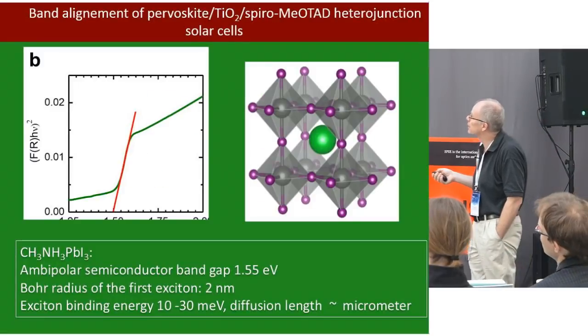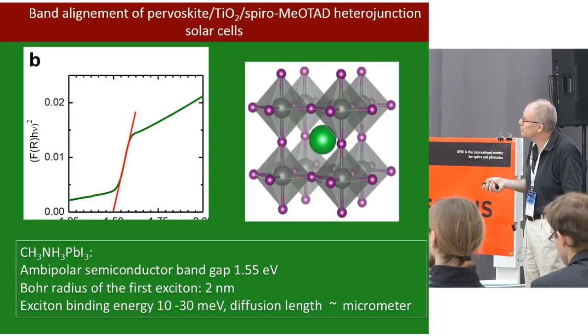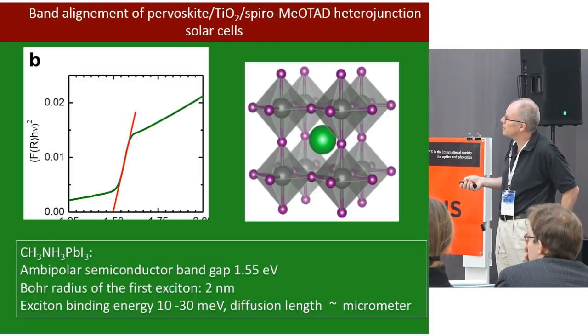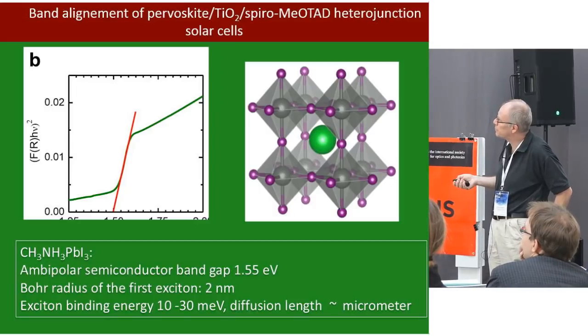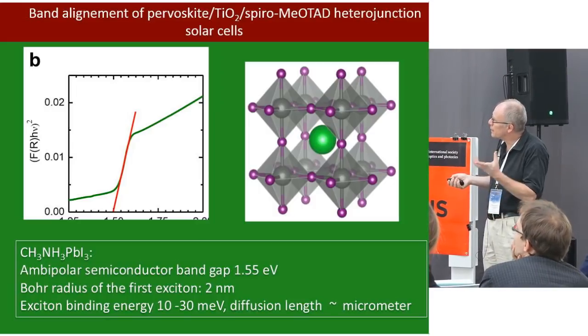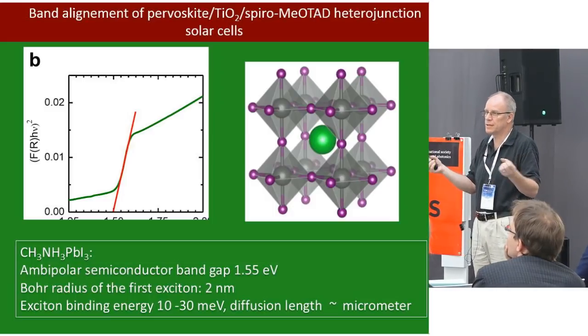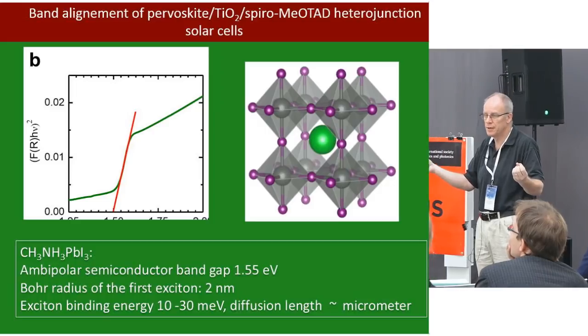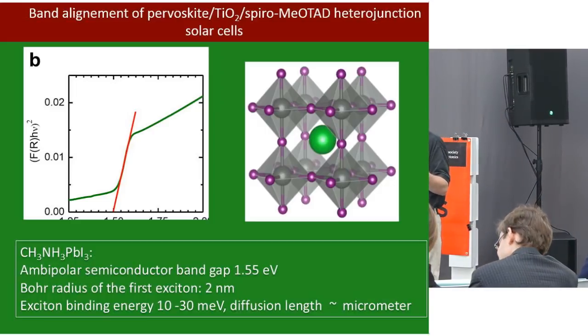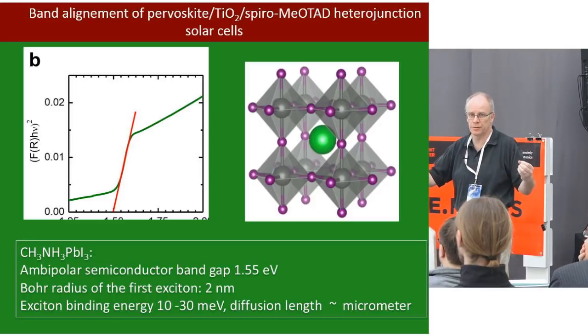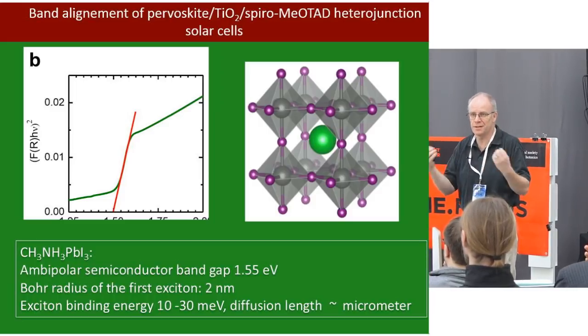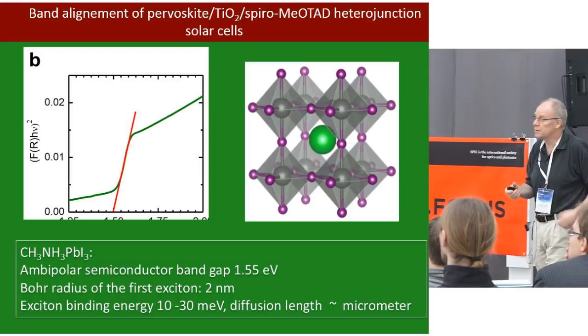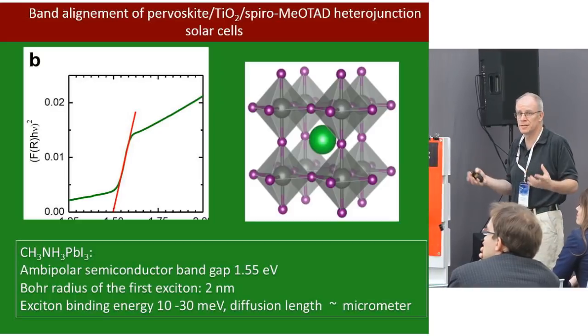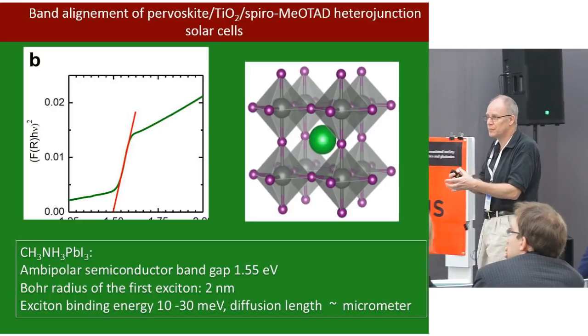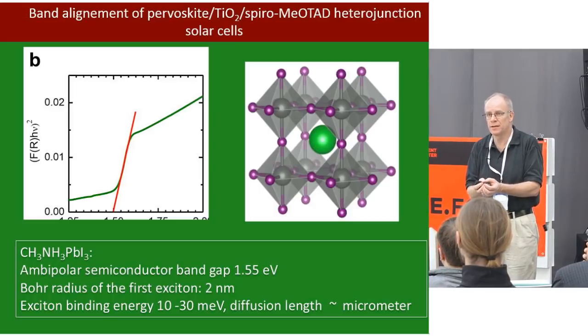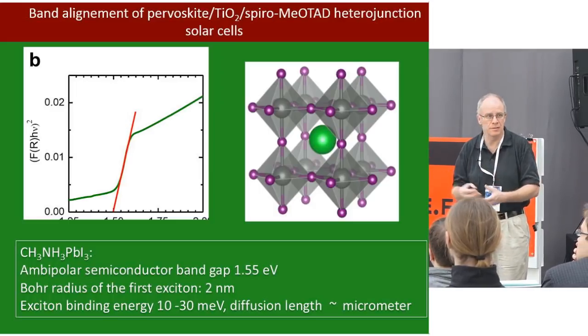In our case, the starting point was methylammonium lead triiodide. It has a good band gap for solar light absorption, 1.5 electron volts. When you excite it, the separation is very efficient. It doesn't take any energy to separate electrons and holes. And the recombination of electrons and holes is slow enough that you can transport the charge efficiently to the contact. And of course, this raises a lot of questions. Why is it like that? How can we design it? And so on. So there are a lot of fundamental questions. But in short, it's a perfect semiconductor. It has all the criteria to be an efficient solar absorber. And you can make them in minutes in the lab, in a chemistry lab.